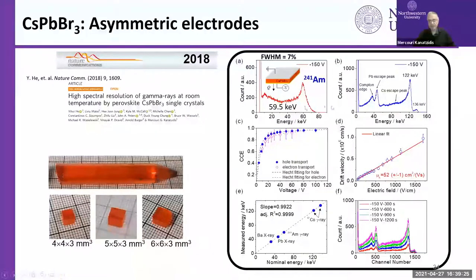Here you see the resulting spectra from an americium gamma ray source, which emits gamma rays at 59.5 keV. We can resolve this peak. This is the cobalt source, which emits at 122 keV and 136 keV. We can also resolve that. So this was great. We were very excited to see that.